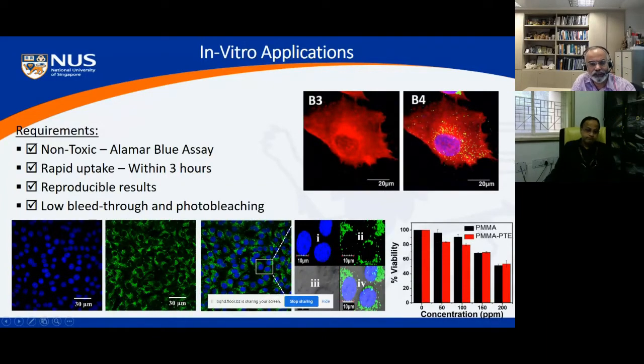I'll show you. And then we can also see whether this is toxic or not toxic. And we go from 0 to 200 ppm. 200 ppm is already quite concentrated, right? So then you start seeing the toxicity. At a lower concentration, we don't see much toxicity, at least for the polymethyl methacrylate.